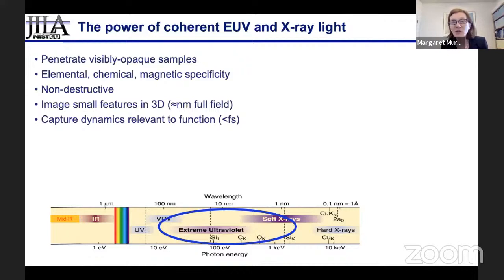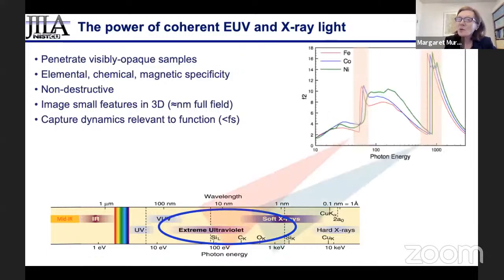X-rays by themselves, even incoherent sources of X-rays, are extremely powerful tools. They can penetrate visibly opaque samples, and they have inherent contrast. So if you have an X-ray beam, you can tell what element one is looking at by the position of the absorption edges. And also the chemical state or the magnetic state is encoded in these positions. Under many conditions, one can implement non-destructive imaging.